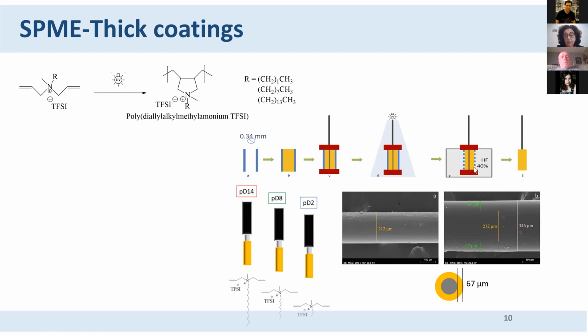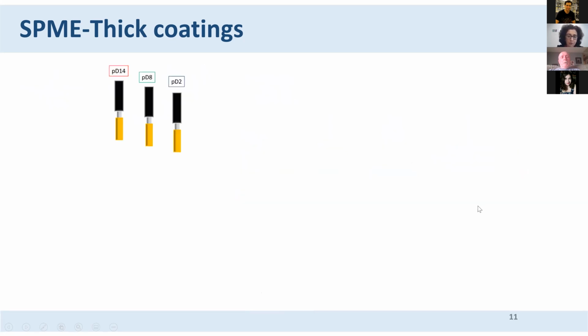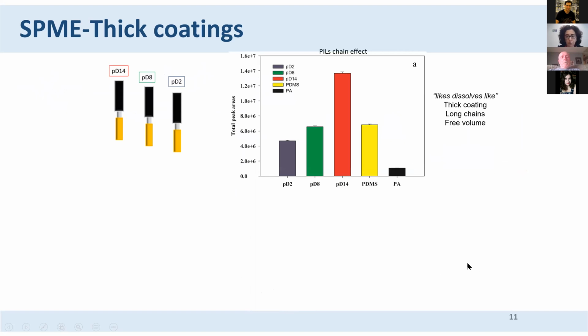However, it did not allow the flexibility to play around with the thickness of the coating. So we prepared 3 fibers with each one of these polymers that we have here. And we can see here that the fibers were 67 micrometers thick. So let me show you what we did with these fibers. This was David's first work.